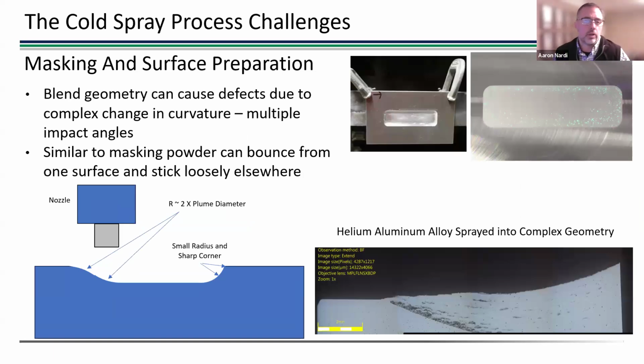All right, so similar to your masking issue, the way you blend a material makes a huge difference too. So you can see here an example on the bottom left. I've got two different methods of blending. The first one on the left of that image shows a very gentle radius, a large radius. I put there as a rough order of magnitude about 2 times the plume diameter. And we've found generally if you're in this very large curvature regime, you're going to have pretty good quality of your cold spray material. So you can follow that kind of a curvature with your plume if you want and get really good deposition quality.